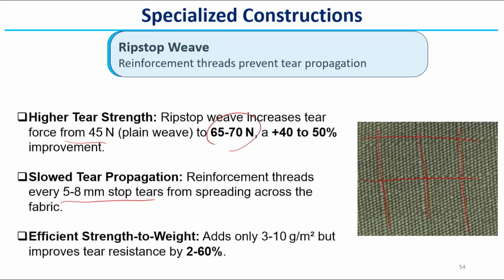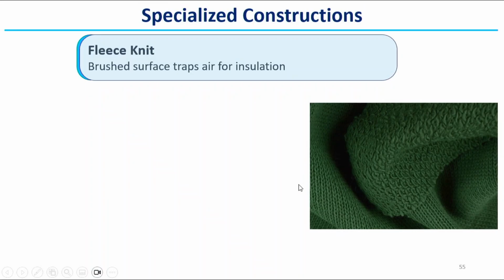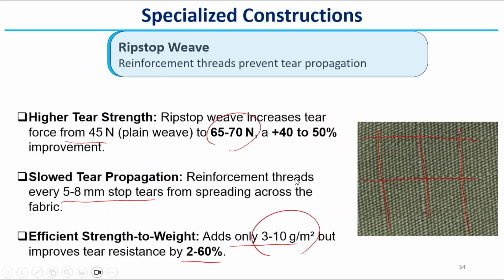Efficient strength to weight ratio. So, we can add 3 to 10 gram per square meter due to the reinforcing thread, which improves the tear resistance. So, that is important. Here you can see 40 to 50% enhancement in the tear strength. Basically it is a typical 20 to 60% increase generally if we increase the weight. So, typically it is around 40 to 50% improvement in tear strength.